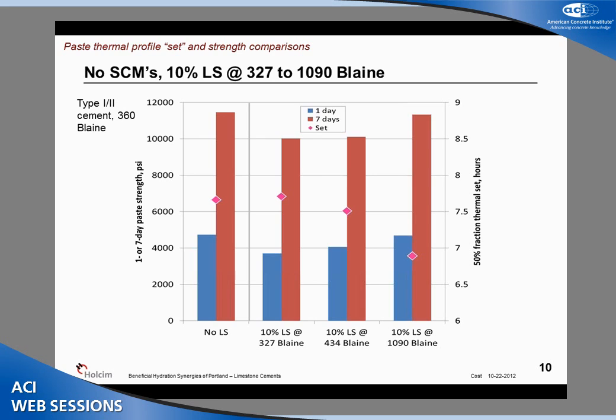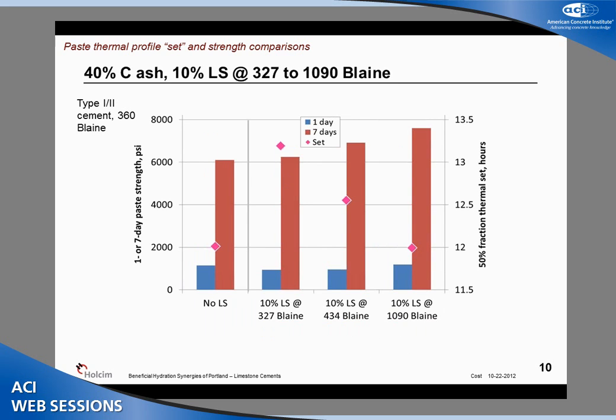I don't have 28-day data on this, unfortunately, for this paste without any limestone replacement of the cement. And this is the axis for the thermal setting times that we observed, which are indicated with the diamonds. And as you can see, when you go to 10% limestone replacement with the coarse limestone, the strength performance is detracted initially until you begin to make that limestone finer. And at a certain point, you can actually essentially recapture the lost strength from the 10% dilution of Portland cement. The setting times also become quite interesting because the setting times begin to get faster with the finer limestone. Nothing else has changed in these systems.